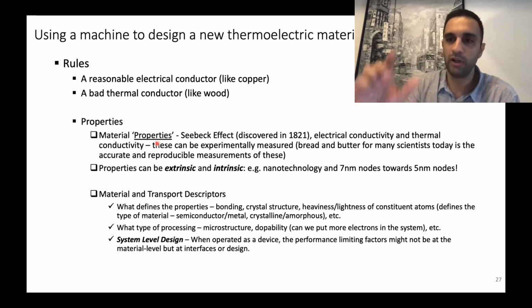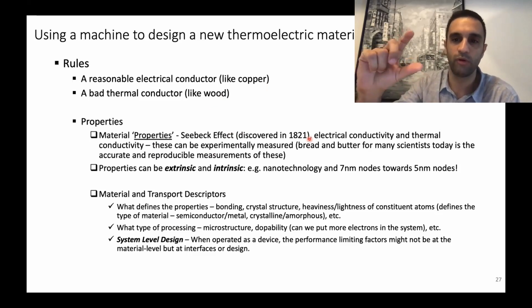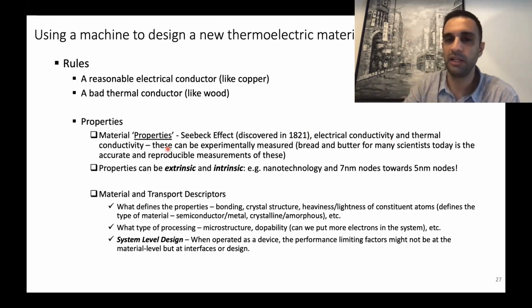If you go deeper into the material properties, the Seebeck effect, which is what I described to you before, the open circuit voltage divided by the delta T, the electrical conductivity and the thermal conductivity, these are linked to the material ZT. But of course, you can do a whole bunch of engineering. They are process dependent, right? You can have extrinsic as well as intrinsic properties. And people working in electronic circuits know this very, very well.